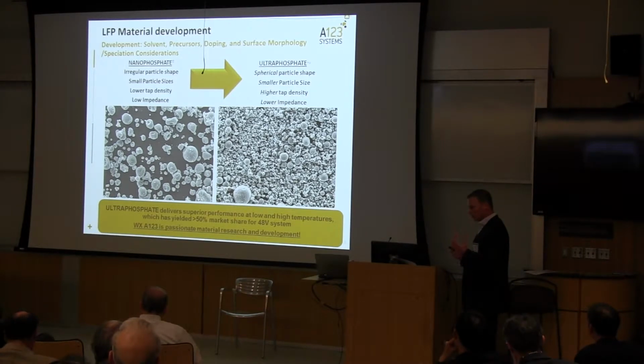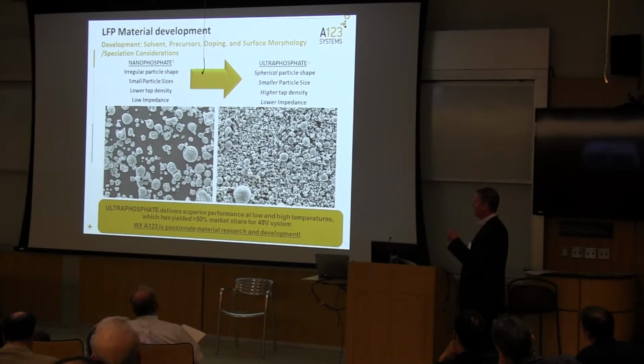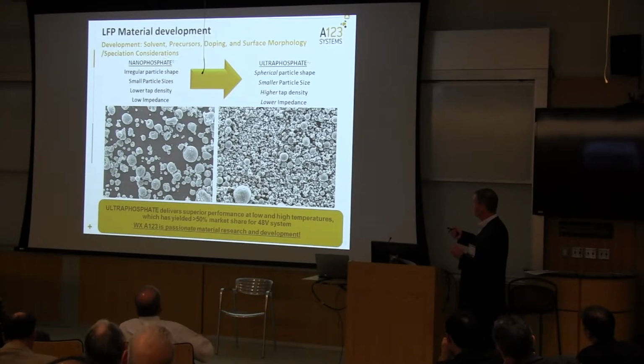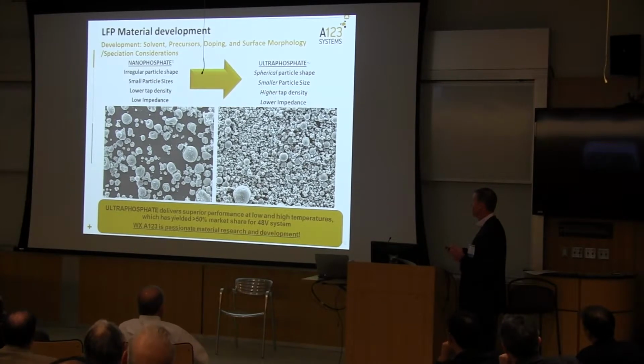A lot of people don't really pay attention to this, but in this particular case, the two key ones were the dopant precursor and also the iron phosphate. Looking at the BET surface area, the density, how that interacts, how that could be milled to get all the components together, but also more importantly, how those precursors actually decompose during the thermal reaction to get the final product, so that you can actually control the speciation on the surface of the material. So again, I kind of highlighted all that together in terms of solvent for the slurry, precursors, doping, surface morphology, the speciation on the surface. All of this is really, really important.